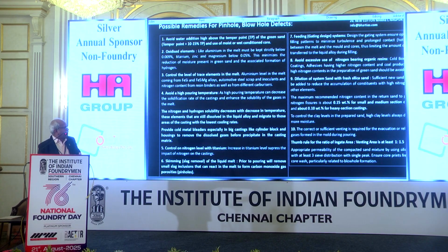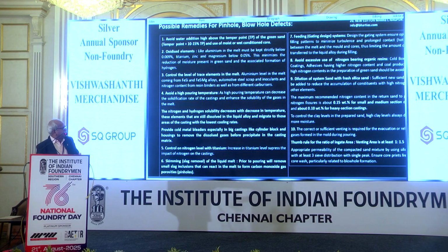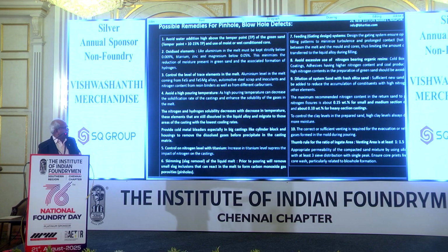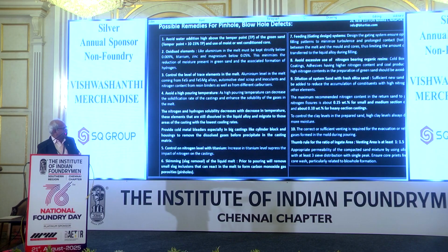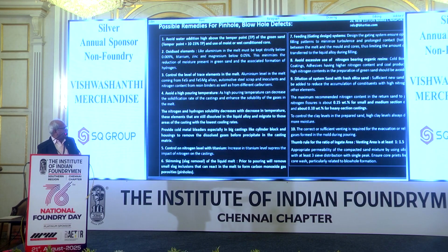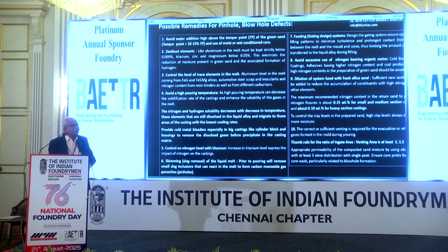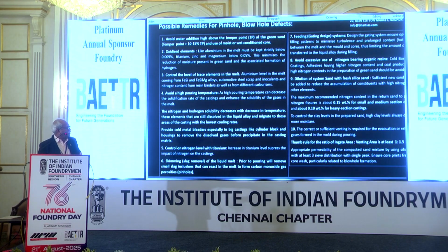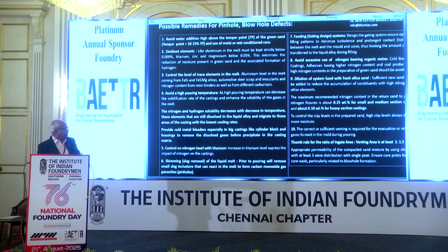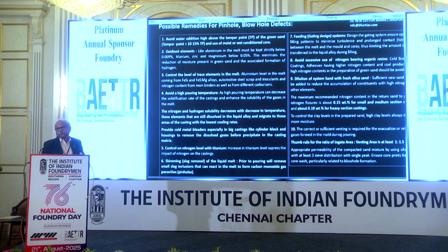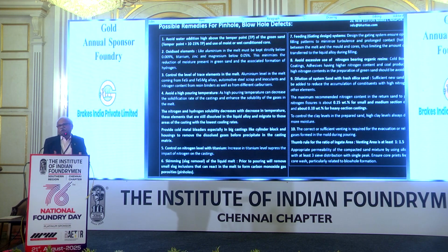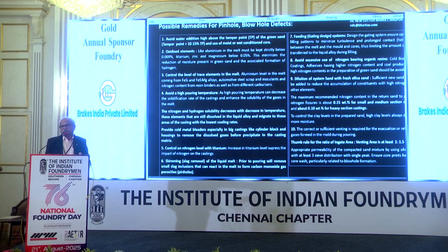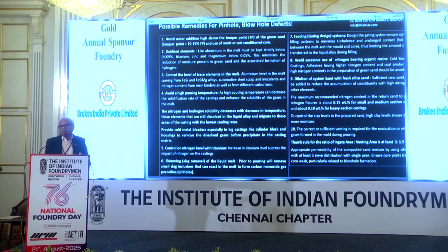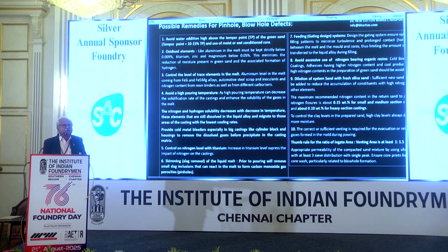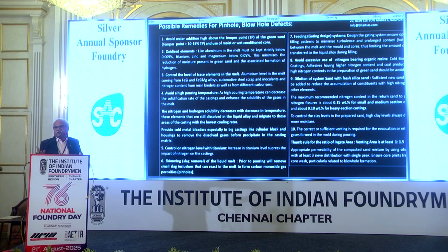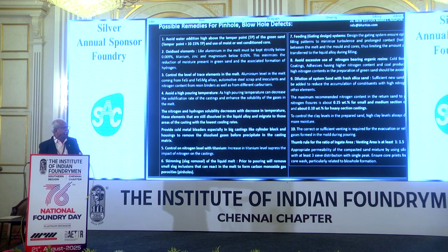The maximum recommended nitrogen content in the return sand to avoid fissure defects is about 0.15% for small castings, and 0.1% by weight for medium to heavy section castings. Control the clay levels in the prepared sand, since high clay levels always mean more moisture. When you increase the clay level, to get the strength, to make the sand homogeneous and to achieve the desired compactability, we need to add more moisture. So more clay again means more moisture and generates the defects.